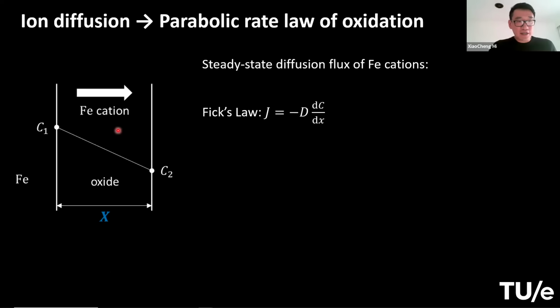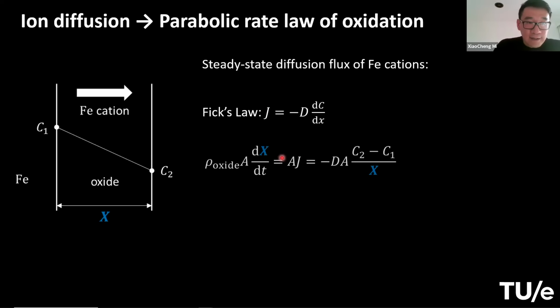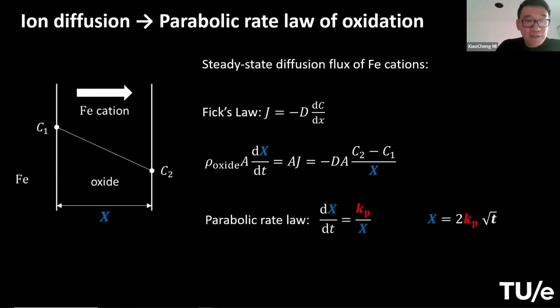And the diffusion is mainly described by Fick's law. We also know this from heat and mass transfer that we study for gas phase combustion. This Fick's law depends on the difference of concentration over the thickness of the oxide layer. So basically, this is the gradient of the concentration of the ion across the oxide layer. It depends on the difference and inversely on the thickness of the oxide layer. The growth rate of the oxide layer depends on the diffusivity times area, of course, and the gradient of concentration. And this can be written in this form.